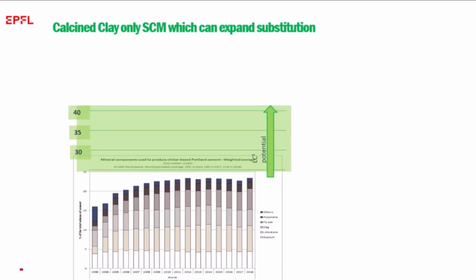Now, if we remove this limitation by bringing calcined clays into the mix, we can easily go to a level of substitution of 40%. Nobody's really argued with me about that, on average we could go to that average level of substitution, and that would represent a saving of 400 million tons of CO2 per year. To put that in context, that's 10 times the emissions of Switzerland, where I'm from. It's something like between 1% and 2% of the entire world emissions.